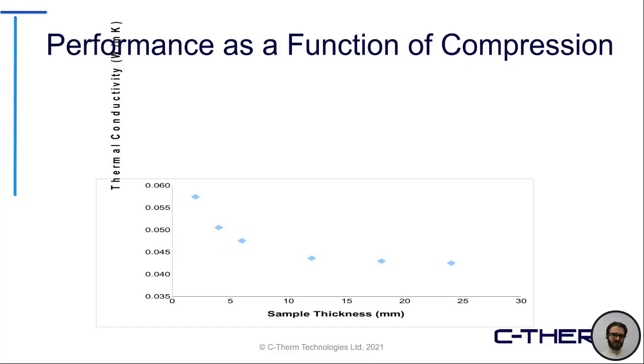Really, looking at performance as a function of compression, you can see that as you increase the compressive load, therefore resulting in a thinner or decreased sample thickness, this will result in an overall higher thermal measurement, in this case thermal conductivity as the metric, but this can be scaled through for effusivity as well, depending on the material that is being tested. The effect of the sample's compression load will influence the overall measurement of that material.